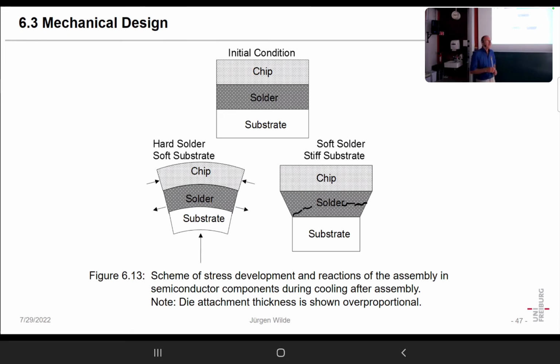Another thing that is important when we look at stress phenomena: up to now we have regarded two materials operating against each other, but that's normally not the case. For instance, we have a chip, a solder, a substrate. Solder can also mean adhesive, it can also mean sinter layer or such a thing. So if we cool down, and both would cool down more or less independently, that is when the solder is really soft, or when the adhesive is soft. Both operate more or less independently. And so the solder or the adhesive will take up all of the strain difference here. That means the stresses in chip and substrate are not so high, but the deformation in the solder is much higher. And that means the solder can crack.